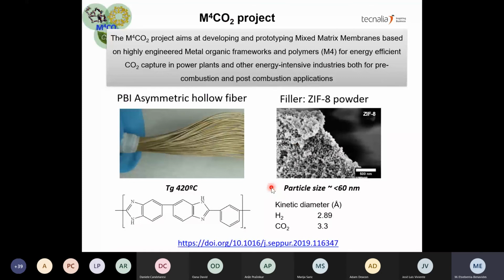Tecnalia's activities on PBI mixed matrix membranes started in the M4CO2 project. This project aims to develop a prototype of mixed matrix membranes based on metal organic frameworks for both pre- and post-combustion CO2 capture. In that project, several polymer and MOF pairs were tested in the flat sheet configuration. And in the case of pre-combustion CO2 capture, PBI was selected as polymer matrix and ZIF-8 as MOF filler to go to hollow fiber configuration.